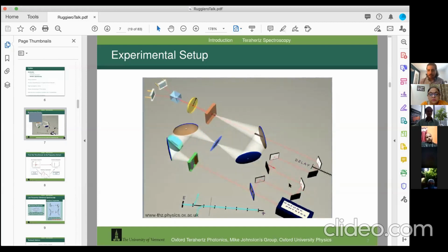So that's coming through this delay stage. What that actually does, the terahertz introduces a birefringence. We measure the polarization of the 800 nanometer pulse, and then we delay through in time. What that does is it allows us to sample the whole terahertz waveform on a point-by-point basis in time.